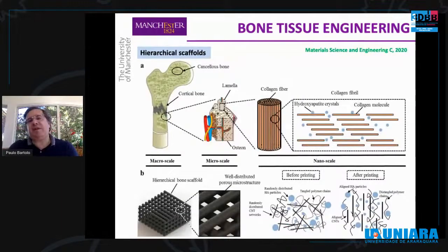Another area particularly relevant for us is the design and fabrication of hierarchical scaffolds. We published a paper this year showing this approach using an extrusion-based process to create PCL, hydroxyapatite and multi-wall carbon nanotube scaffolds, mimicking the micro and nanoscale structure of bone. In this paper, we showed that the multi-wall carbon nanotubes were aligned along the printing direction, similar to the collagen fibrils in the bone, with nano hydroxyapatite particles interdispersed between the multi-wall carbon nanotubes, acting as the natural hydroxyapatite crystals in bone.